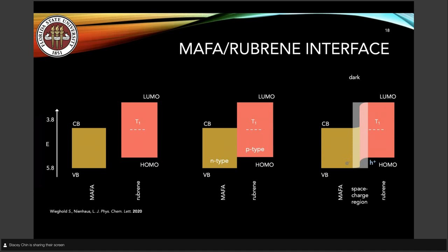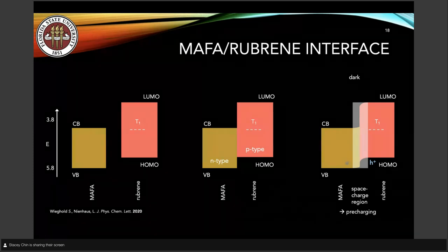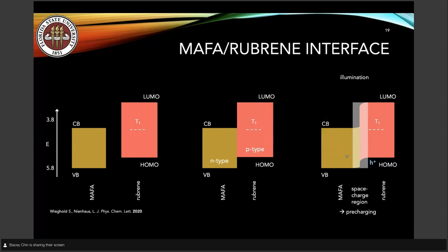So this is all in the dark. So this creates a space charge region. And what we call this here is essentially pre-charging of our organic, because you're already populating the rubrene with holes. If you now send in a photon, you excite the electrons from the valence band to the conduction band, and these can then undergo energy transfer or electron transfer to the triplet state, thus creating the triplet that we're looking for.